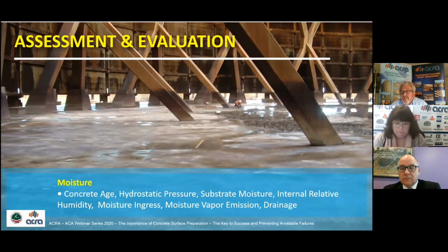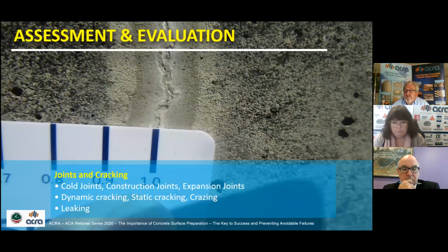Also moisture. Moisture can be through the maturity of the concrete, if it's fresh concrete. We've also got to look at hydrostatic pressures, substrate moisture content, the internal relative humidity that we test by putting a probe into the slab or into the structure. Moisture vapour emission, is there a vapour barrier present or is there no vapour barrier? Is the area subject to drainage? All considerations.